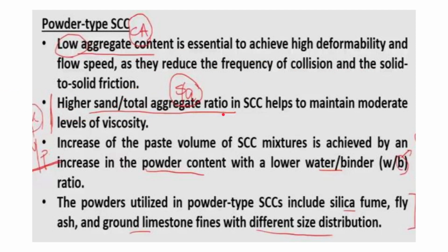A higher sand to total aggregate ratio in SCC helps to maintain moderate levels of viscosity. That is also an added benefit, and this ratio was defined as S by A, if you remember from the initial classes. The increase of the paste volume of SCC mixtures is achieved by an increase in the powder content with a lower water binder, W by B, ratio. So the more the binder, the lower will be the water binder ratio.